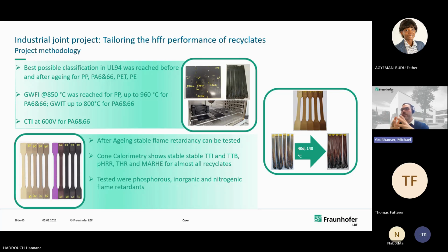We also did cone calorimetry, and it also showed really stable materials, reasonably stable values for the time to ignition, time to burn, peak heat release rate, total heat release rate, and the medium average release heat rate. And for almost all the recyclates we did, there were some materials that ran out of the scope. But also here, similar to the first project, the problem was most of the time the polymeric quality.